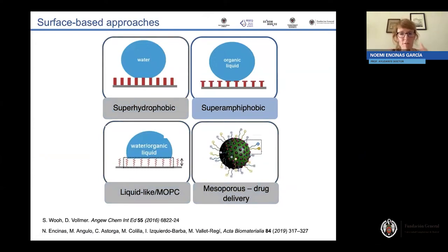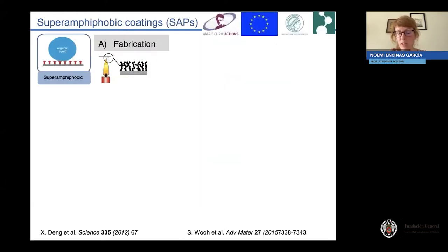Now going to the superamphiphobic surfaces, here one can think, okay, so what is the main difference? The main difference is that by having a certain roughness and also a certain hydrophobicity on the surface, we can define a superhydrophobic surface for water, which is a liquid with a high surface tension. But what is going to take place if we have a low surface tension liquid is that it's going to be prone to wet the surface because it's not able to overcome these capillary forces and gravity forces. So whenever we are thinking about oils or even blood, we need to add an extra layer of roughness. A surface which is capable of avoiding being wetted both by water and organic liquids is a so-called superamphiphobic surface.